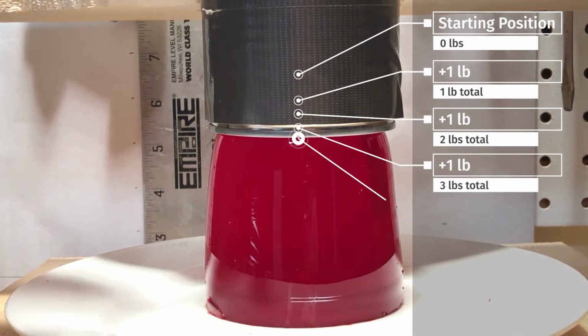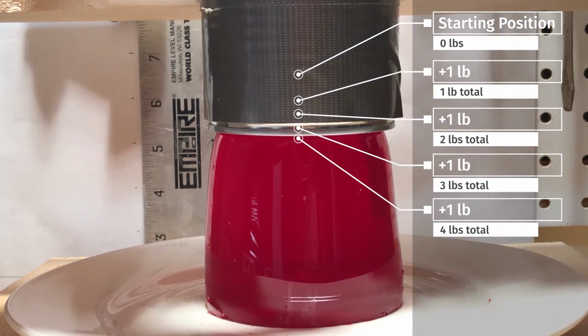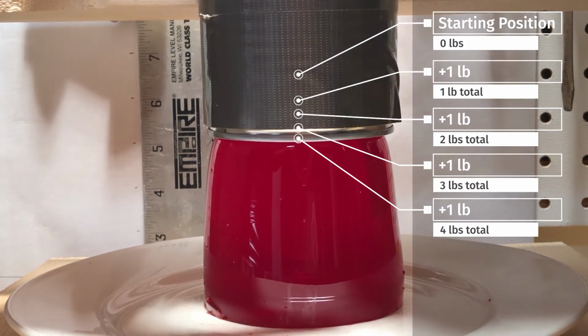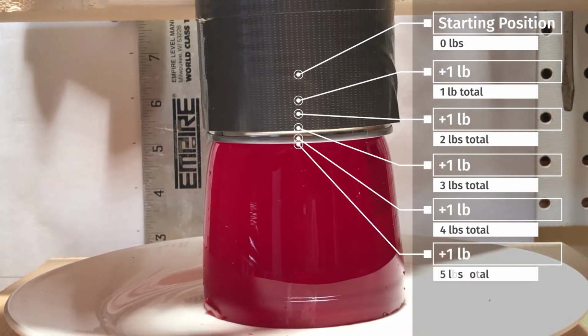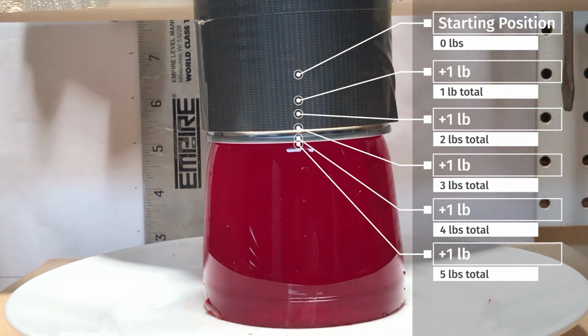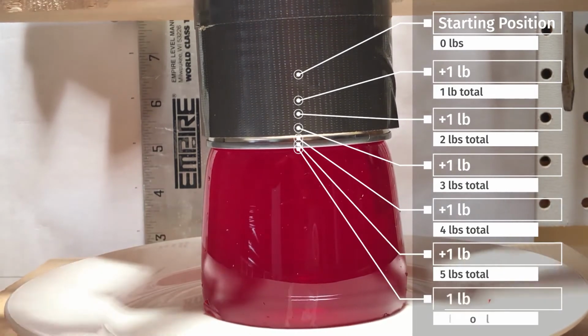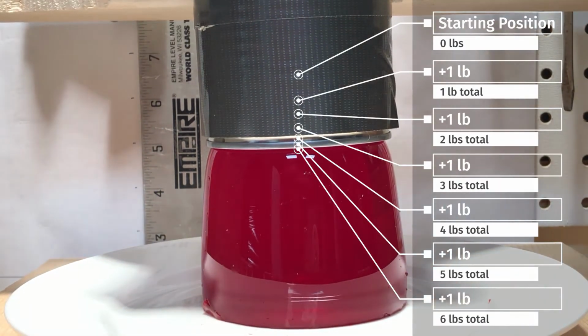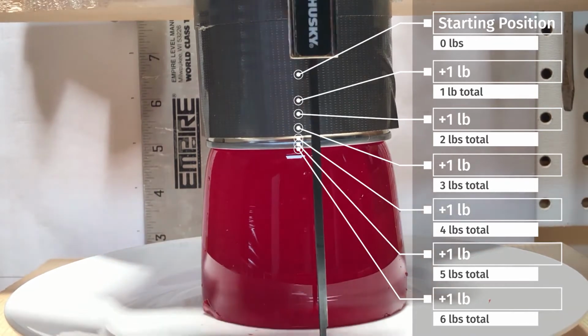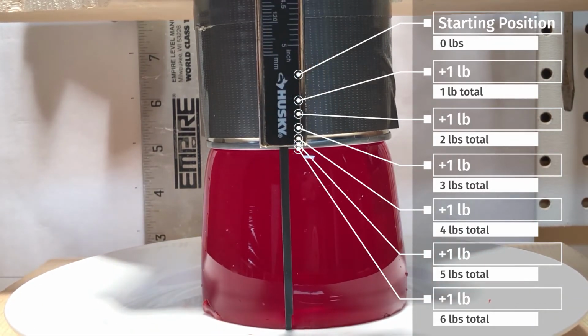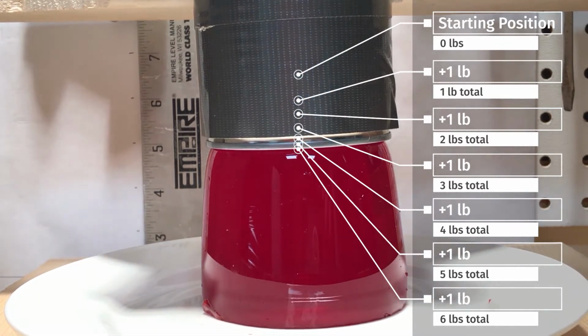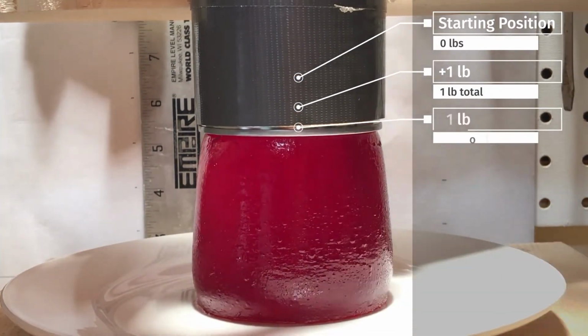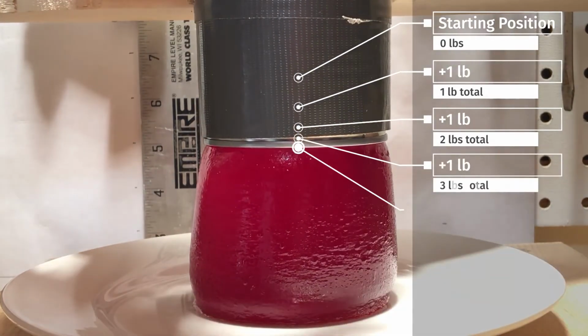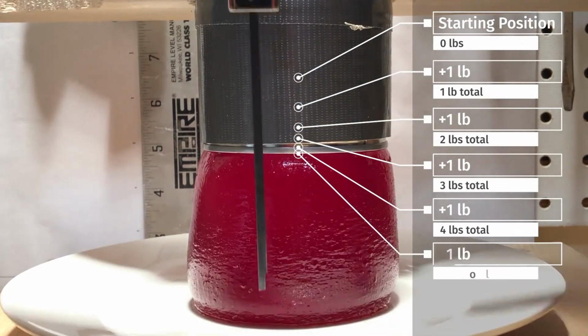In Jello, we apply a load of 6 pounds, and remembering that the diameter of the sample is 2.5 inches, that makes a 5 square inch area for the sample. 6 pounds divided by 5 square inches equals 1.2 psi. Under that load of 1.2 psi, the sample shortened by 31%. For generic gelatin, 5 pounds of load, or equivalent to 1 psi of stress, shortened the sample by 29%.